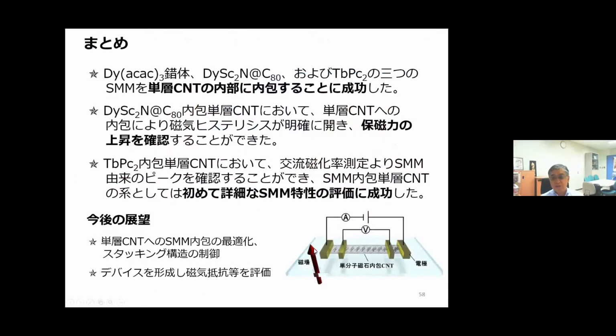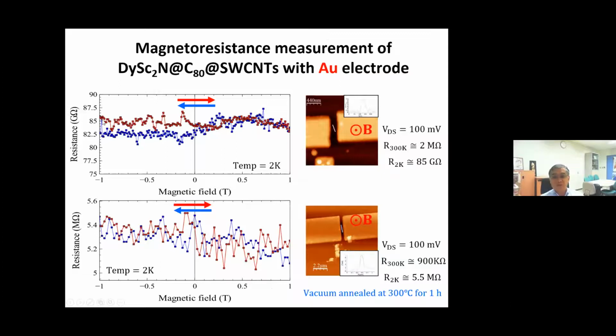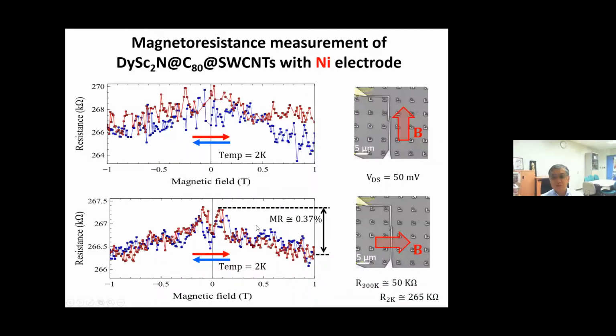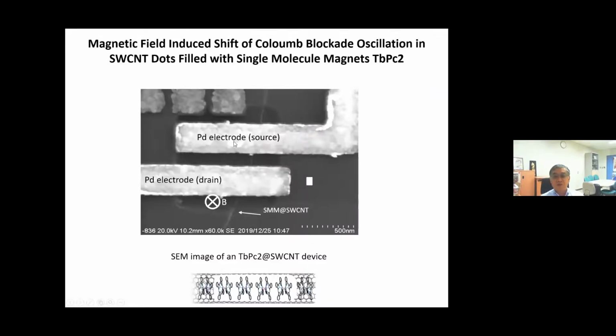I'm sorry, it is Japanese, but we put one carbon nanotube by lithography, put the electrode. So this is a gold electrode. Okay, with this gold electrode and this single carbon nanotube, parallel and perpendicular, no magnetoresistance. But we switch from gold to nickel. You can see magnetoresistance observed. Very small, 0.37. But we observe the magnetoresistance for the first time in the metal fullerene single molecule magnet inserted in the single carbon nanotube. And also a magnetic field Coulomb blockade.